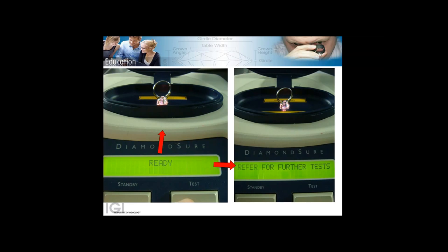So a simple way is, at all our labs in India, we have simple equipment which is kept. You can take a cut of the parcel. You just send a cut of the parcel to our lab, and we'll quickly tell you whether the stones are passing under the DiamondSure. If they say pass, okay. If they say refer, we can tell you that so much percentage of stones are refer. If they're below about 3-4%, they're still okay to go ahead with the parcel.